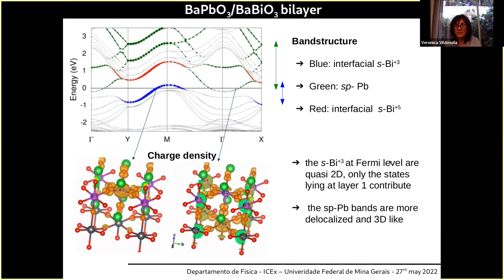So we can say that we have S bismuth 3+ states at the Fermi level that are quasi two-dimensional, and that come mainly from layer 1 at the interface, and the SP lead bands that are more delocalized and 3D-like at the Fermi level. So you have two types of electronic states.